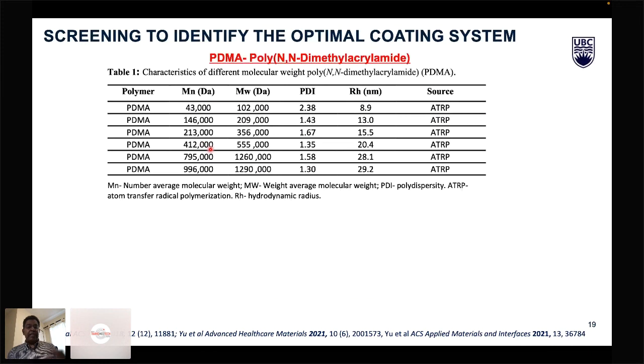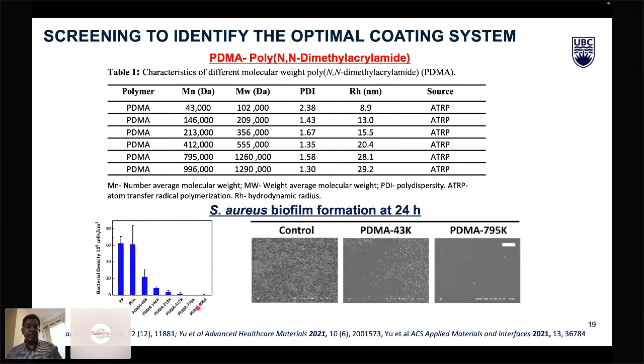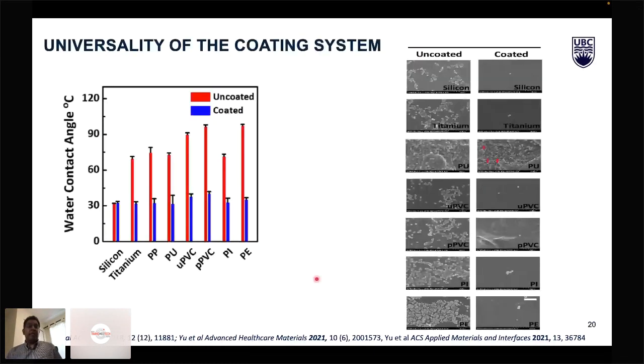Then we looked at changing the molecular weight of that, and what we found is that molecular weights in the range closer to 800,000 to 1 million Dalton, in combination with dopamine, we were able to generate a coating which is very resistant to biofilm formation. This coating can be applied to the surface by a dip coating process or a spray coating process, and it is universally applicable to many different substrates. We can see the example shown here on different substrates, and the bacterial adhesion is almost prevented.